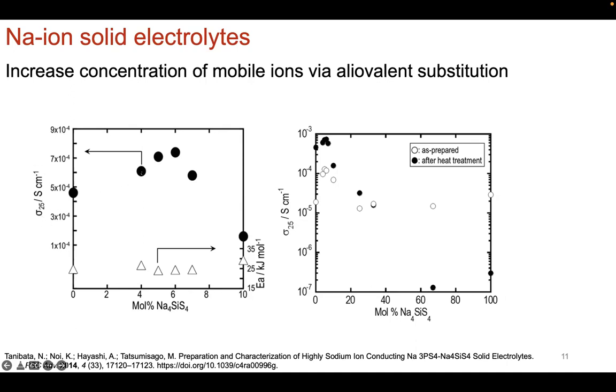So you do see increases as a function of increasing molar percent of how much you put in, and then you start to see a decrease. So there's usually a nice middle ground where you introduce aliovalent substitution, you introduce disorder, but then after that, there's quite a bit of drop off with the end members. Okay.